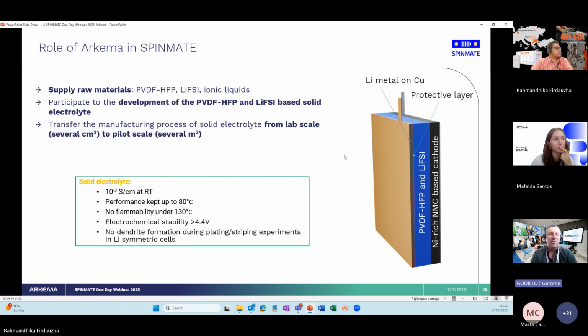Just some clues about the specification of the solid electrolyte. We want to reach a conductivity higher than 1 millisiemens per centimeter at room temperature, while keeping performances up to 80 degrees and no flammability under 130 degrees. Electrochemical stability has to be higher than 4.4 volt to be compatible with NMC 811. And the most difficult part is no dendrite formation during the plating stripping experiments in symmetric lithium cells.